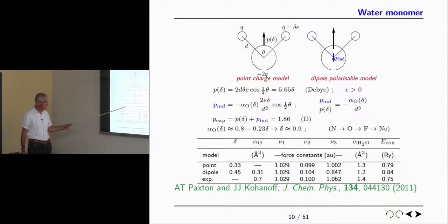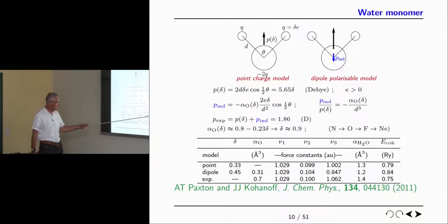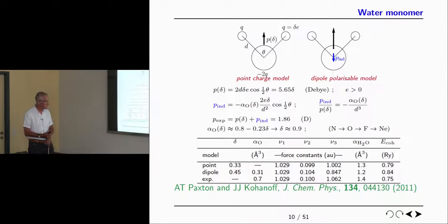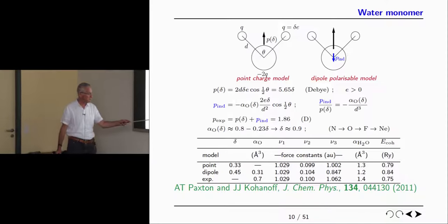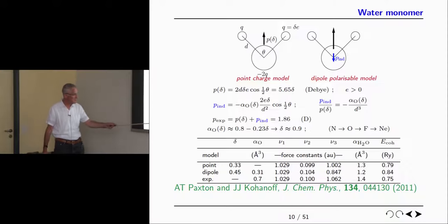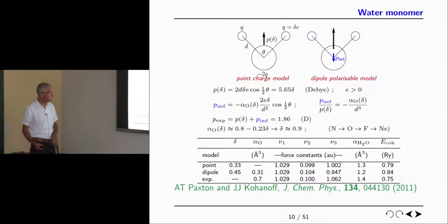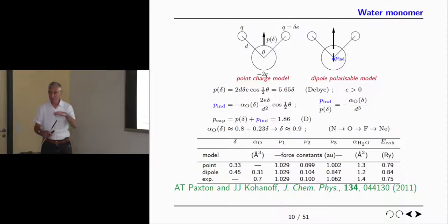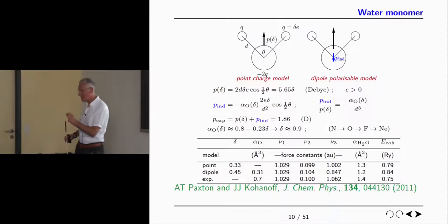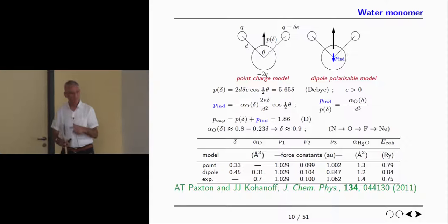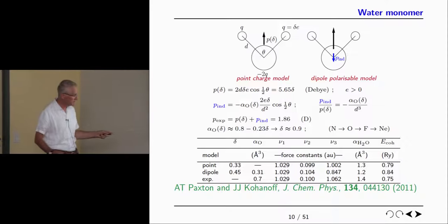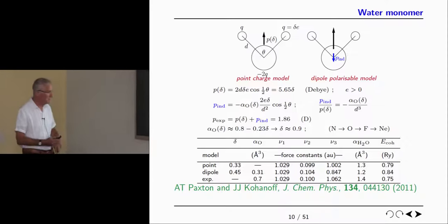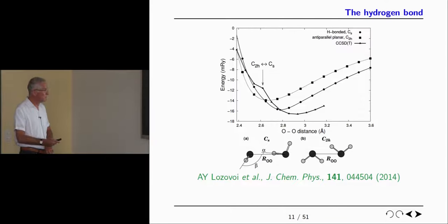So we have the parameter delta, or the U, and we have the polarizability, and then we have a dipole model for water. And we were very happy because one can reproduce even the force constants, which is a subtle problem. We can reproduce the polarizability of the entire molecule and even its binding energy. So that's where we were. It was a sort of bottom-up creation of a model for water, starting with the monomer, and then we went on to the dimer. But I'm going to jump a few years, because this is what we originally published, and now we had Sasha Lozovoy, the postdoc, working on it for three years or so.